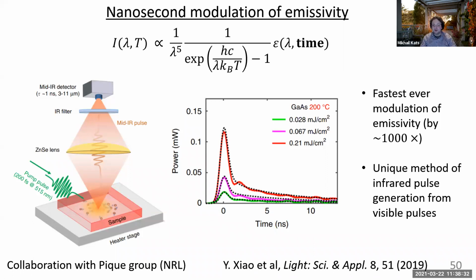And we did account for that when we built our models. I didn't talk about this, but this dotted line over here is a model of what's going on in all of these cases. And in fact, carrier cooling or something? Yeah. So you have carrier heating and then carrier cooling, and all of that is hidden. Actually, there's a very large sharp pulse that happens on a time scale of about 1 or 2 picoseconds here in this material, but you don't see it because the detector responsivity is only about 1 nanosecond. So it's hidden in this peak.